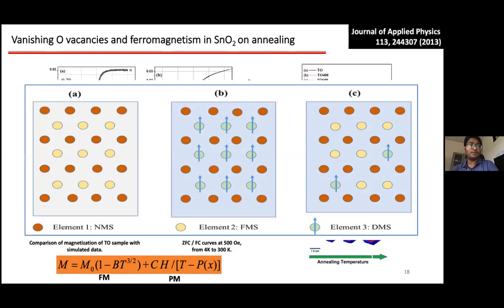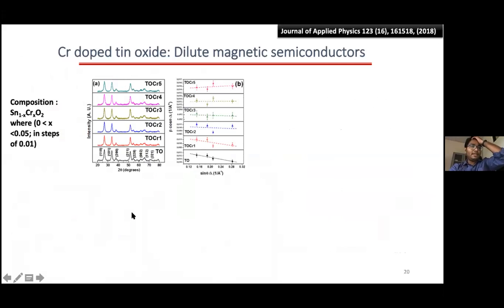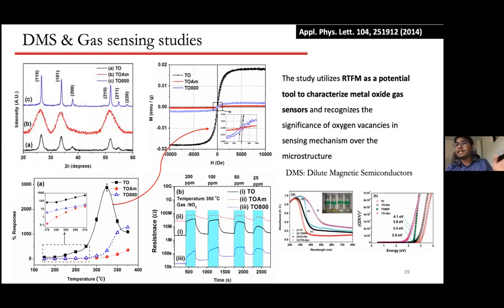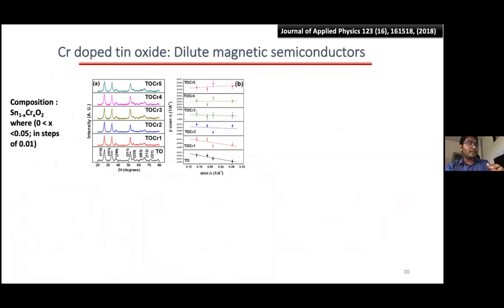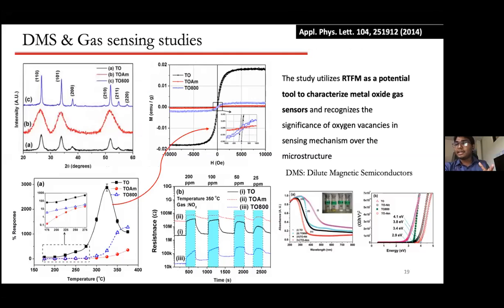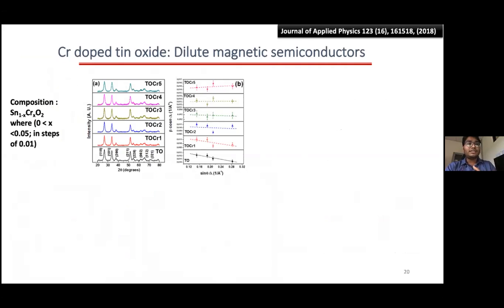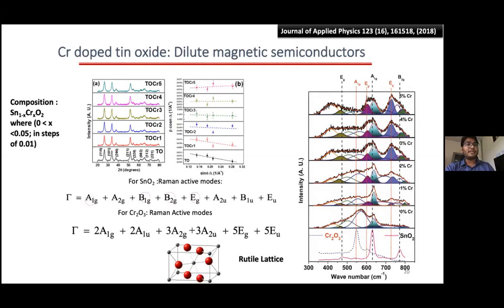So we did some more work based on that, and tried to synthesize this by various other ways, and tried to dope it with some magnetic ions to see what happens to these moments. And chromium, which is also not really magnetic, it is not like iron, cobalt, nickel, it doesn't have a moment, it's unpaired spin. So the chromium doping enhanced some kind of ordering when we looked into the nature of chromium doped samples, the dilute magnetic semiconducting things.